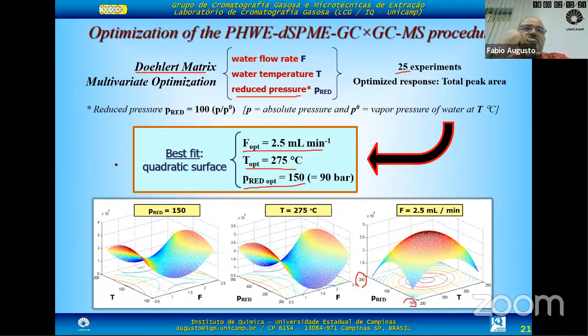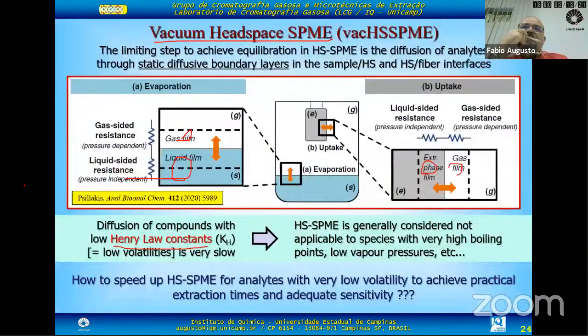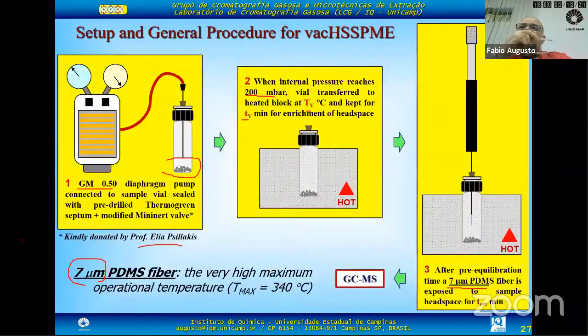Okay, thanks. I have a third one. What level of vacuum is reached in the vial when you do this vacuum HS-SPME? In our case, we lock the pump at the maximum vacuum obtainable, which is 200 millibars. This is 0.2 atmospheres. It's not a very deep vacuum.